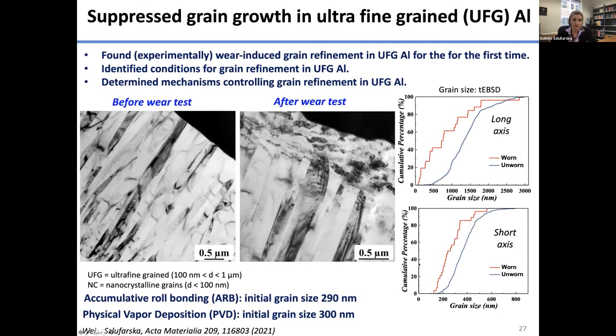Okay, so let's start with the effects of sliding conditions. I wouldn't be sharing this story if we had not been successful in this regard. So I'm happy to report that we have observed wear-induced grain refinement in ultra-fine grain aluminum for the first time. And we have identified the conditions of when that occurs and the underlying mechanisms. Here we have prepared two kinds of samples. One of them is ARB, accumulative roll bonding. The other is PVD. They had comparable grain size to begin with, and it turns out that they had very similar trends with respect to wear.